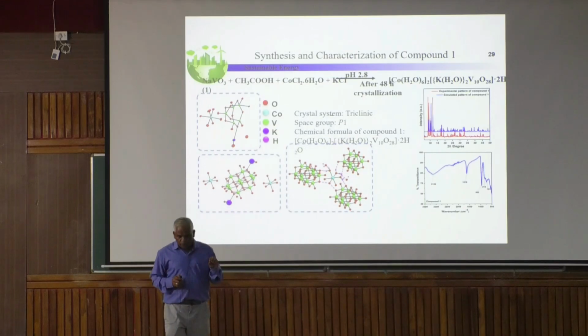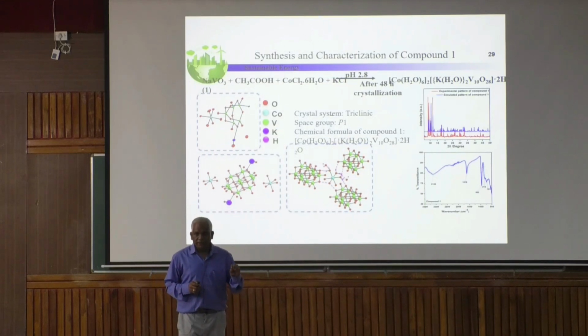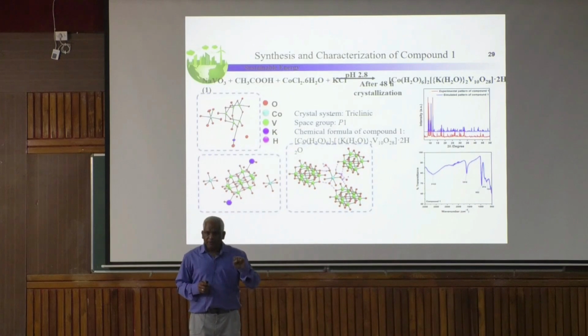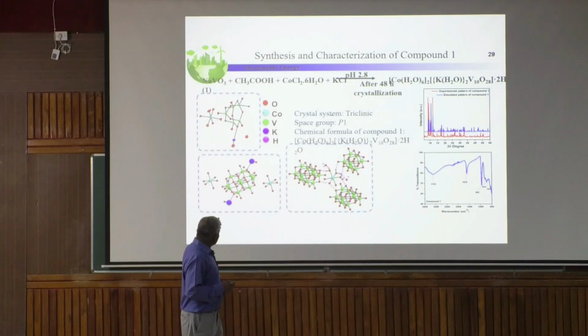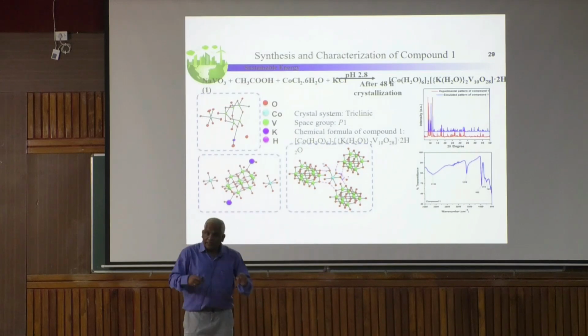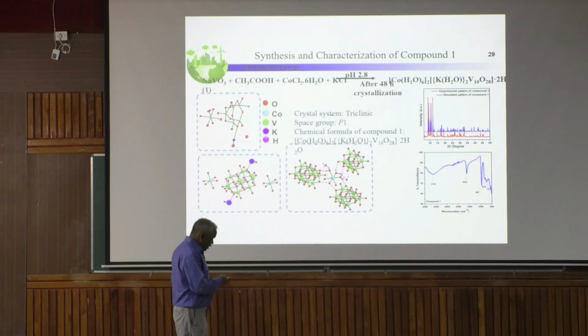Now, for a system to give hydrogen evolution, something has to be reduced, either cobalt 2 has to go to cobalt 1 or cobalt 0, whatever it is, or decavanadate has to be reduced, vanadium 6 to 5, then they can reduce the proton to hydrogen. As such, separately they are not giving. Even the physical mixture was not giving. So what we did, we wanted to know what is the active site.